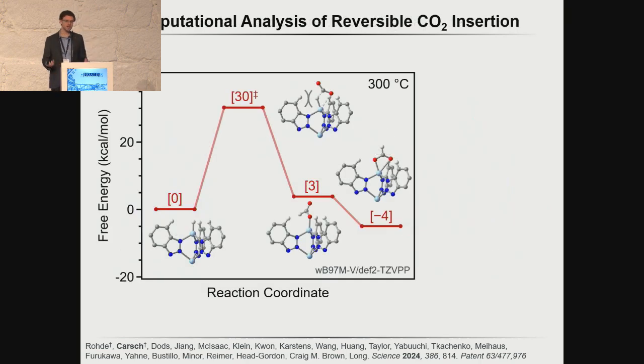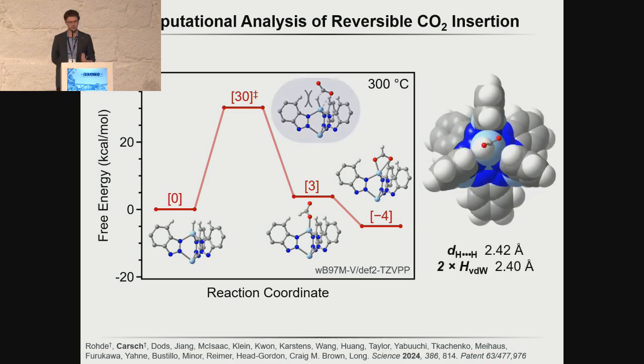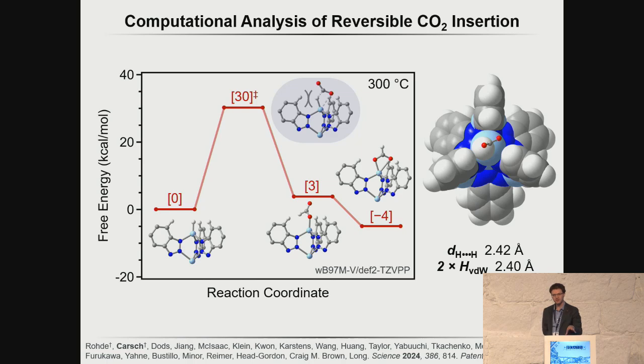And then we can use computations to try to understand the unusual mechanisms of this material. And what we actually find here is that in this transition state for CO2 insertion, the hydride is the nucleophile, the CO2 carbon is the electrophile. There's actually this geometric distortion where the hydride of the zinc hydride has to cant into the ligand, and that actually gives rise to a large penalty such that we need these elevated temperatures to actually undergo the insertion process. And this is quite fantastic. We have a process that has a barrier, and then it is slightly favored at elevated temperatures such that the reaction does occur, but it is a reversible process.